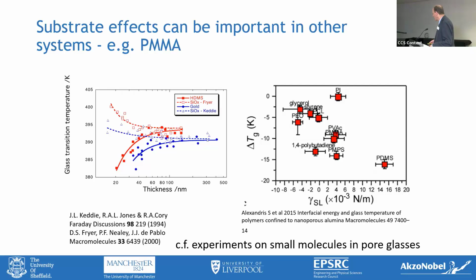And at the same time, some experiments on small molecules in pores actually also showed the same sign. Again, orders of magnitude of 10 to 15 degrees. And again, I say 10 to 15 degrees may not sound very much as a transition, but remember that exponential relationship. And that's probably a factor of 100 or 1,000 in relaxation time. So it's a big deal.